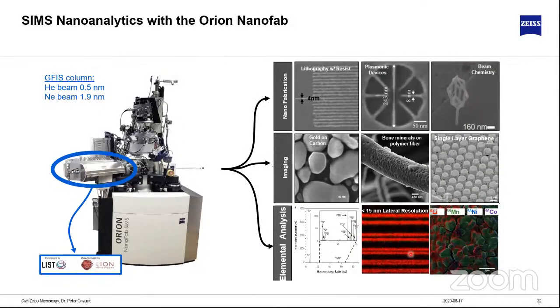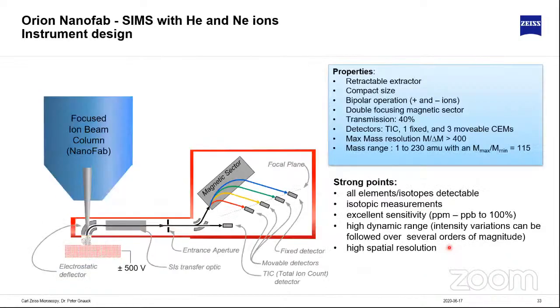Okay, so what I've shown you until now is that we were able to do very good nanofabrication. We can do extreme high resolution imaging. What is missing until now, or what was missing in my talk until now, is analytical capabilities. So one drawback of using ions is we do not generate X-rays. So a helium ion beam at 30 kV does not generate any X-rays. Therefore, X-ray analysis does not work. But what we can do is we can, for example, use our neon beam, generate secondary ions, and do elemental analysis by doing SIMS.